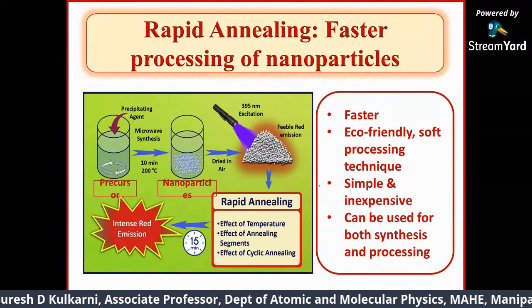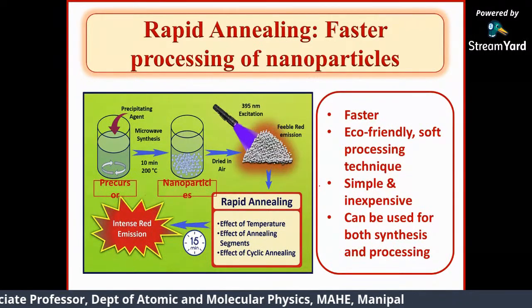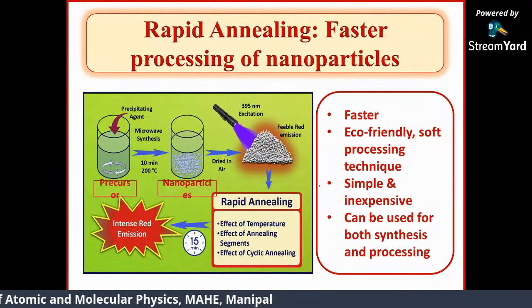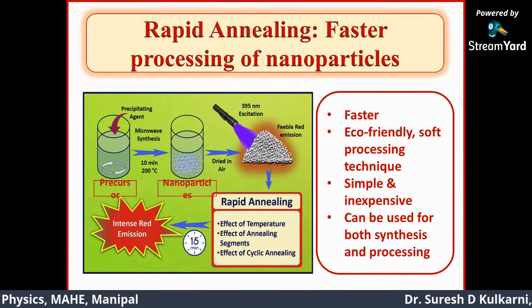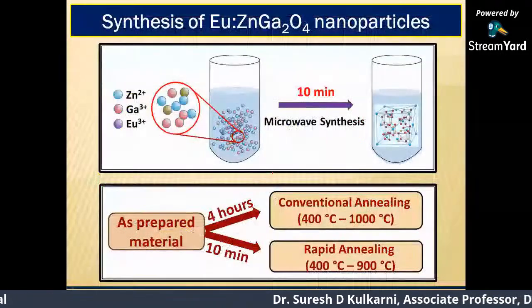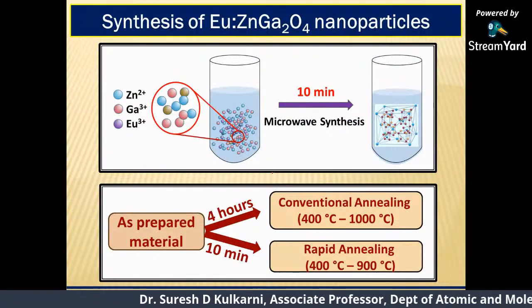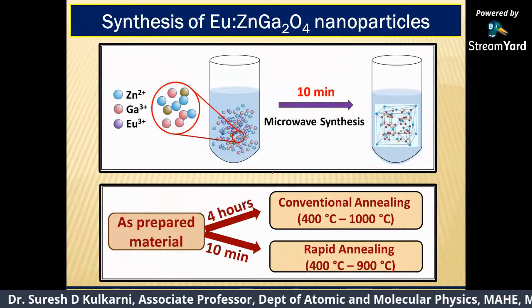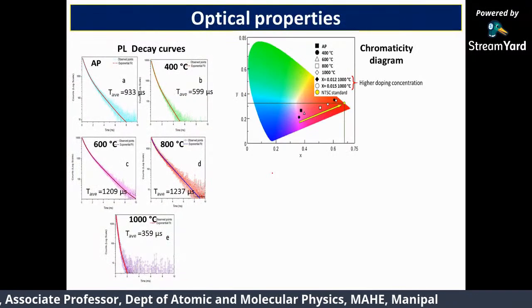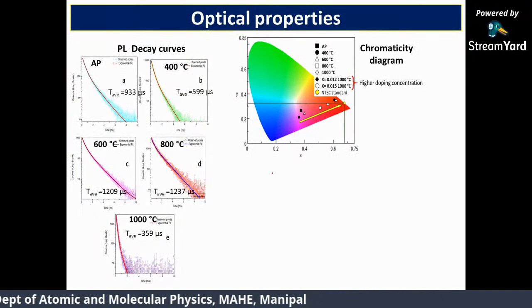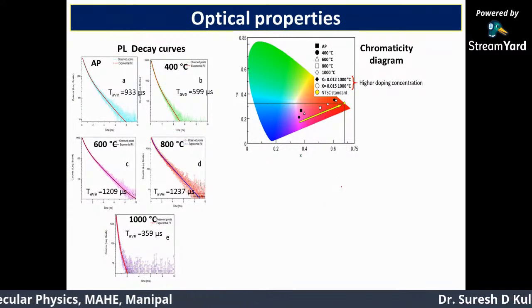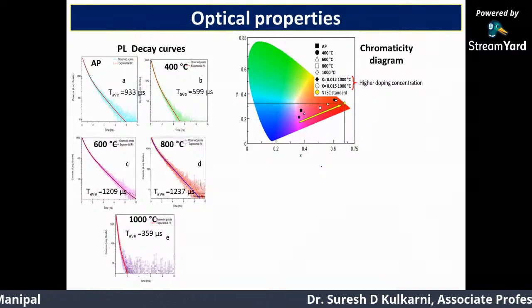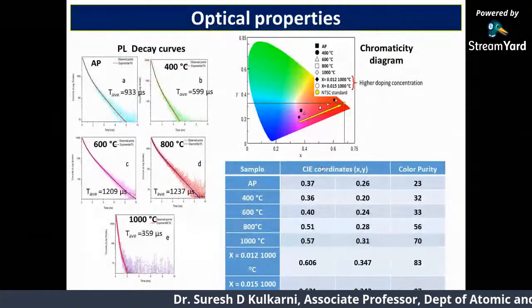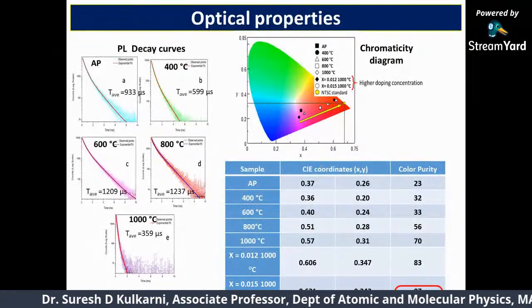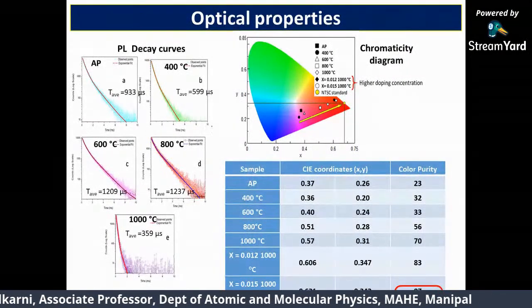In just about 15 minutes of this process of microwave synthesis, after microwave synthesis for 10 minutes in 200 degrees, okay, and a few minutes of rapid annealing, what we have done is we have prepared the europium doped zinc gallate nanoparticles, put it for test, and what you can see here is we are able to tailor the material property to get very good red emission, and with a score of 87% color purity. It is very close to the television set standard. The NTSC standard is here.